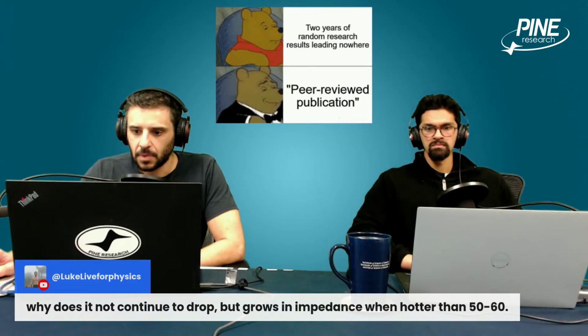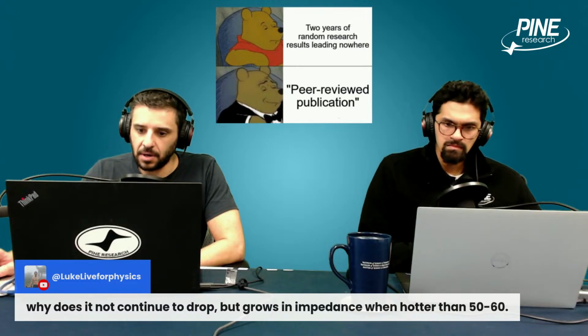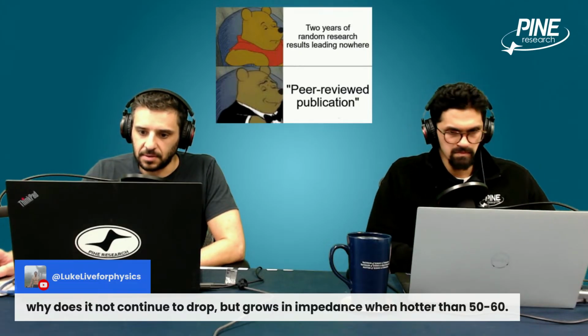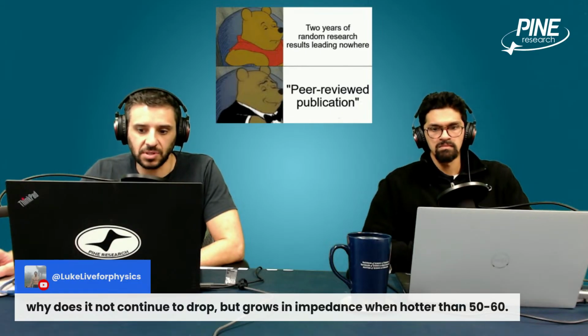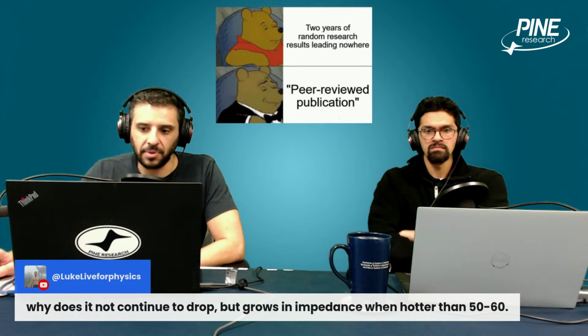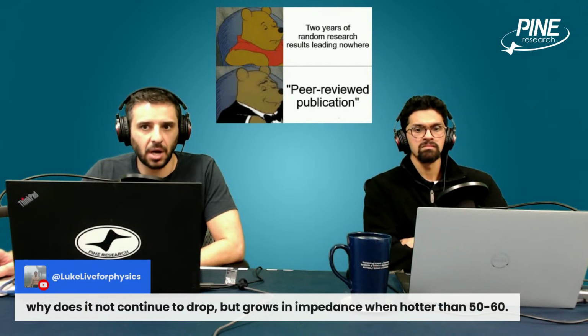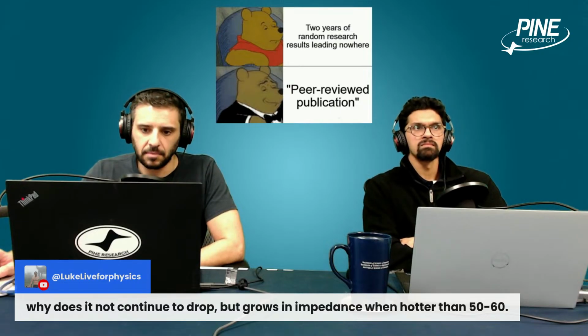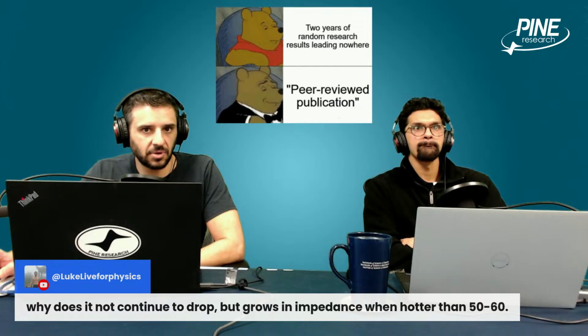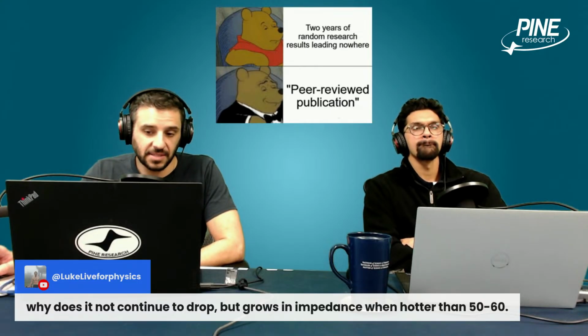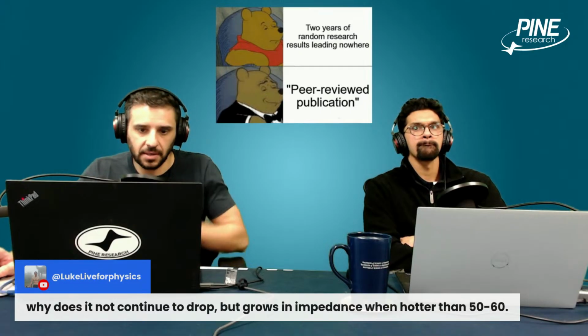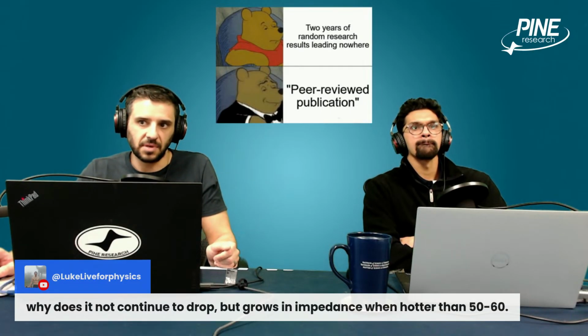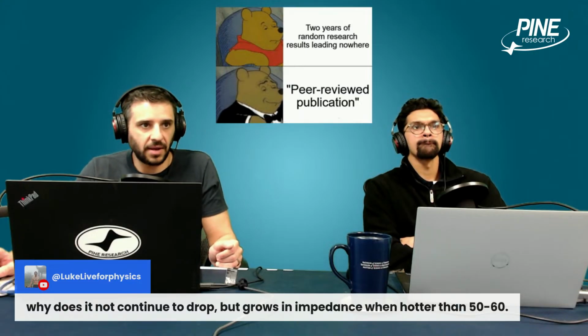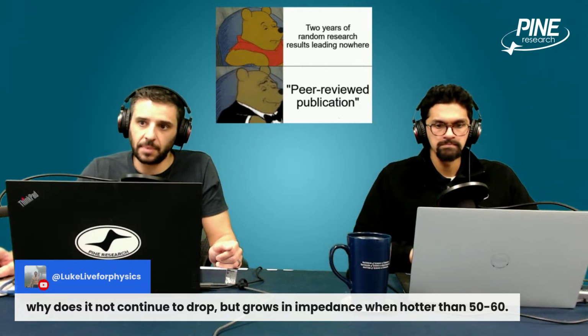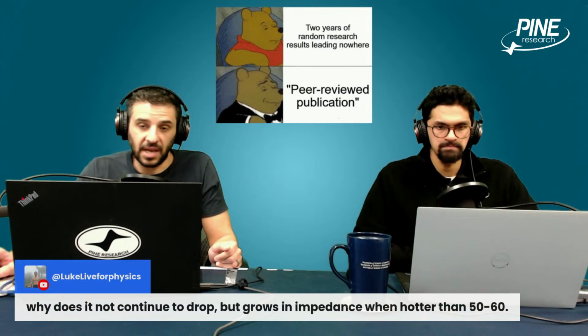So what you're banking on is when you cool it down, that the things that I described are reversible, and they will be to a certain extent. One of the problems with batteries can be how long that can be a reversible thing. Batteries can often be exposed to elevated temperatures and then cooled back down, and they will return to normal. And then sometimes you can do that a bunch of times, and then all of a sudden they go into thermal runaway because you went to an elevated temperature, 70 one too many times, or 80 or 100, whatever temperature it was. You went up there one too many times, you caused the SEI to break down,